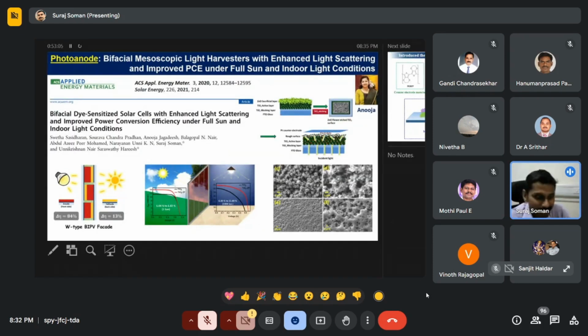So now we will move to the second category of component, which is the semiconductor material that we use. Conventionally, titanium dioxide is used as the standard semiconductor material in all these kinds of devices. As you know, TiO2 exists in different phases like anatase and rutile. The anatase is the most preferable phase used in optoelectronic devices. Here, I'll show you one very interesting work we have done. Normally, for the TiO2 layer, we use nanoparticles with a particle size around 18 to 20 nanometers. When you put 18 to 20 nanometer particles, a lot of gaps or voids come in between the nanoparticles because those are spherical nanoparticles.